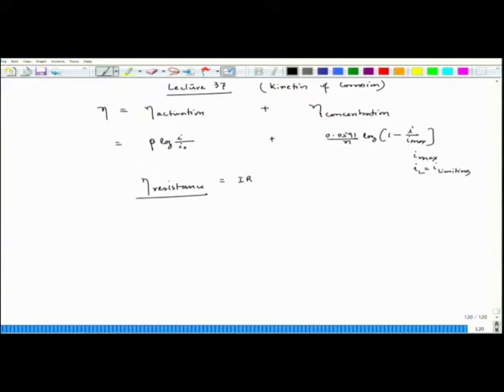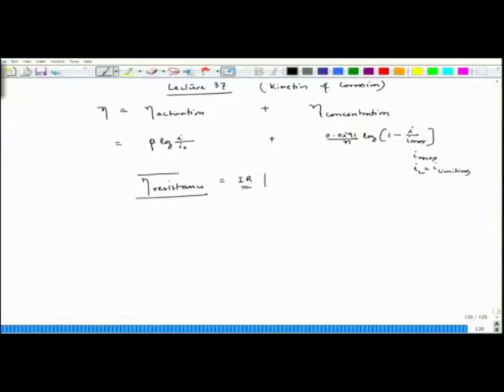But in the case of a corrosive environment, when the metal is immersed in an electrolyte which has sufficiently high conductivity, the IR drop in such a conducting electrolyte is very small, and that is why we will not consider this IR drop in our common corrosion processes. But definitely we will talk about overvoltage due to activation and overvoltage due to concentration effect on the corrosion of a particular metal.